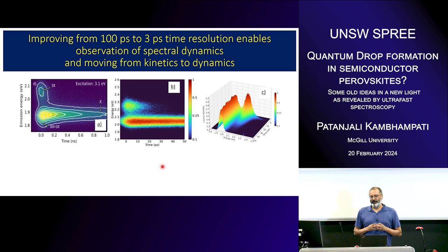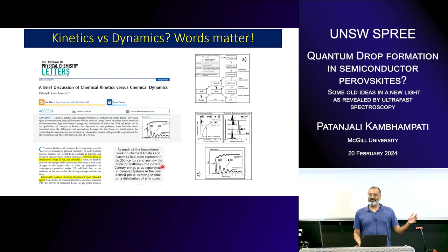That's very important because if anything faster happens in PL, you would miss it. So you want to be able to have the fastest resolution, but not too fast. You don't need femtosecond resolution, but you need about 3 picoseconds resolution, 1 to 3 picosecond resolution to see all the salient PL kinetics and dynamics, which brings up this little statement or op-ed that I wrote for JPCL maybe